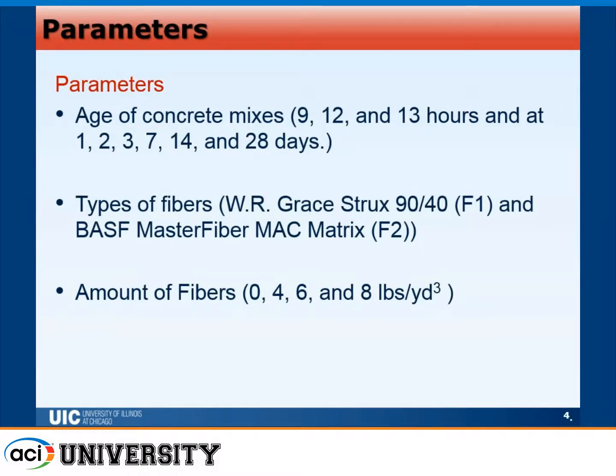The parameters that are taken into consideration in this study, in fact, this study is a portion of a bigger study. The bigger study took into consideration the age of the concrete mixes, different mix designs, and different amounts of fibers and different types of fibers. Age of the concrete mixes can range between 9 hours, 12 hours, 13 hours, 1 day, up to 28 days, as you can see up here.